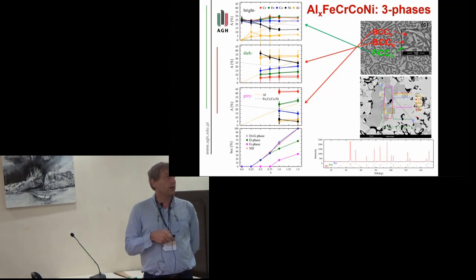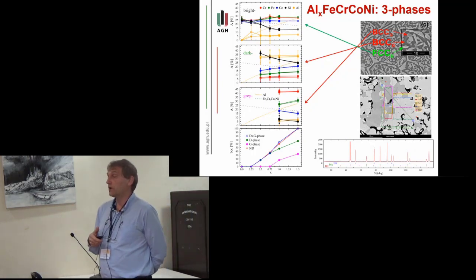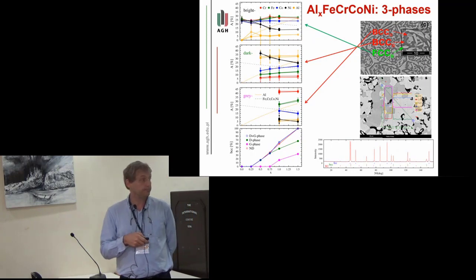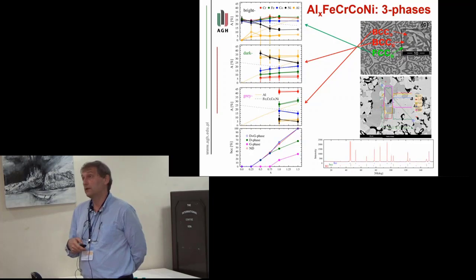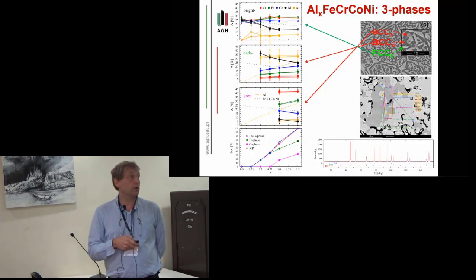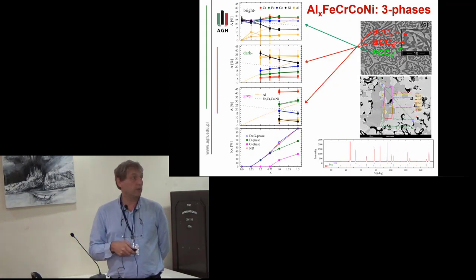We are calling it gray phase; it is enriched in chromium. So in fact we don't observe a single simple structure—we have three simple structures in this case. The X-ray diffractograms or neutron diffractogram in this case are shown here, and they are very well defined. We have several techniques of producing such alloys. We can melt them, we can sinter the pure powders of pure elements and obtain quite large grains of pure structures.